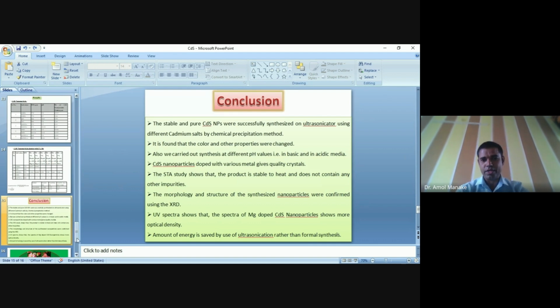We also tried different pH values. STA study also shows that the product is stable to heat. Morphology and structure of the synthesized nanoparticles were confirmed by the XRD. UV spectra show different optical density, and in case of Mg doping, there is an increased optical density. Most important is that much more energy is saved by using the ultrasonication method rather than the conventional synthesis. Thank you, sir.